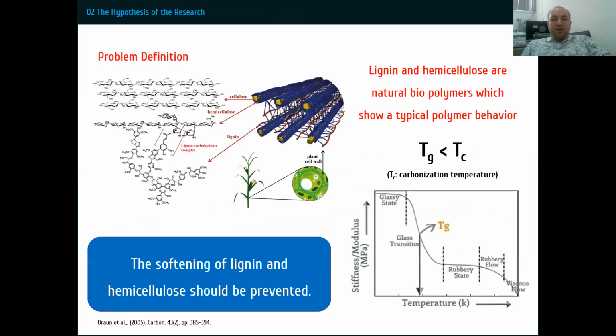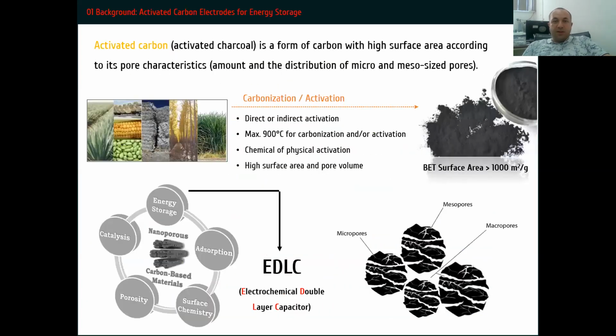As you know, it is a form of carbon with high surface area according to its pore characteristics. It can be synthesized from various carbon sources by direct or indirect activation, and you need maximum 900 C. You can use some chemical or physical agents like KOH, phosphoric acid, or CO2, and you obtain high surface area and pore volume.